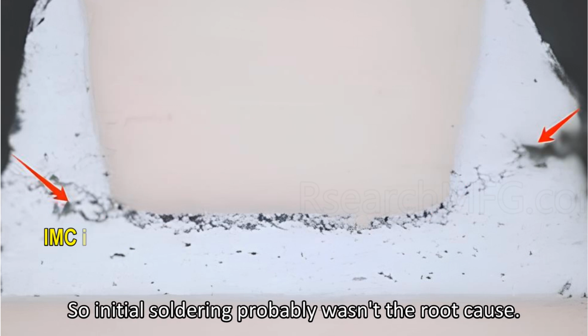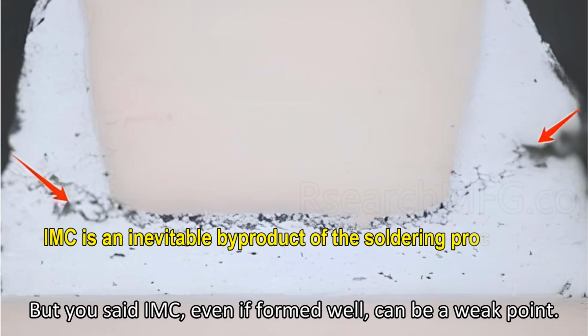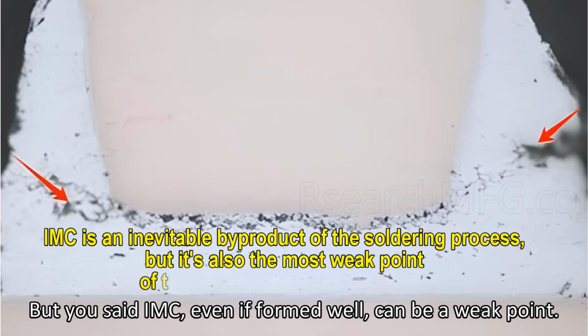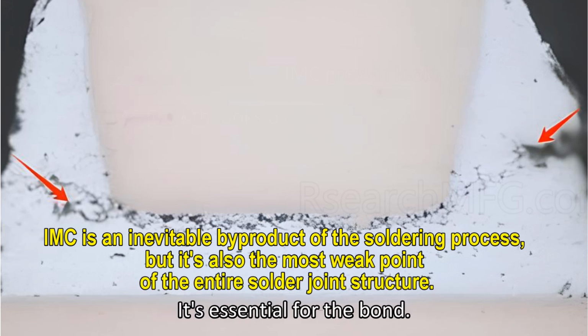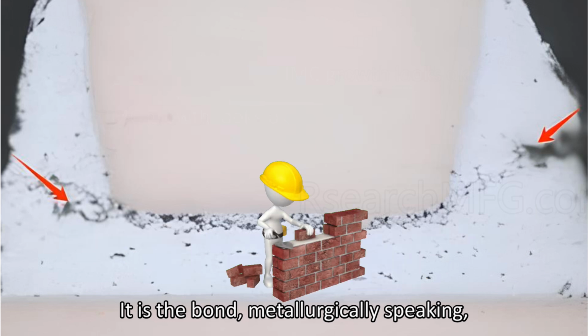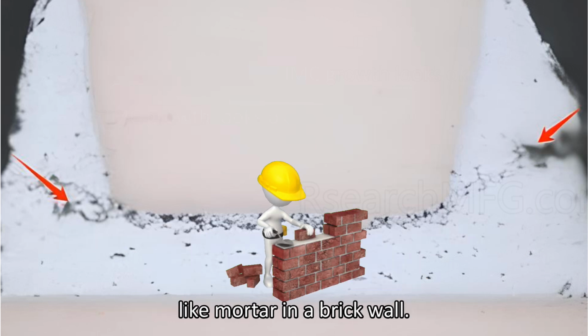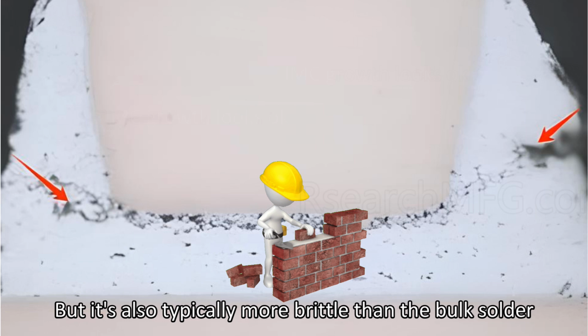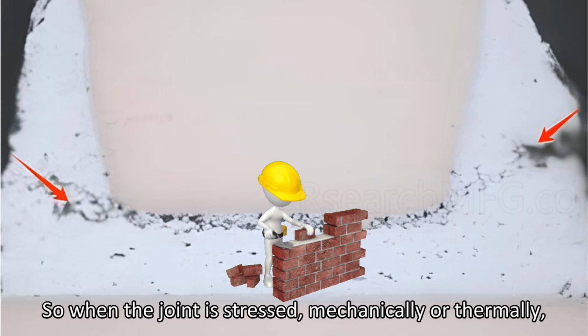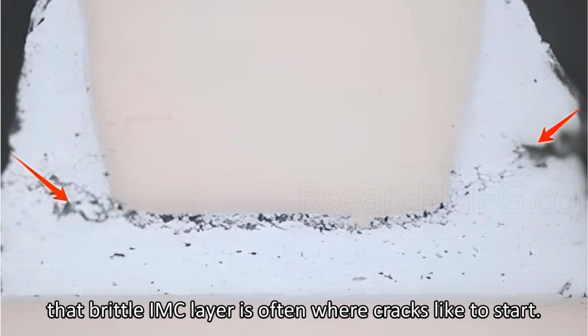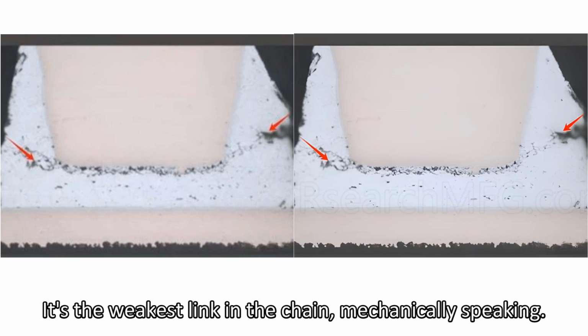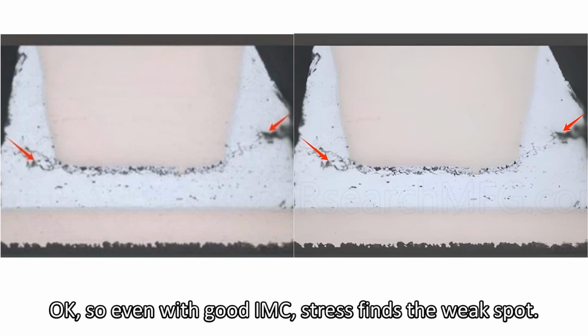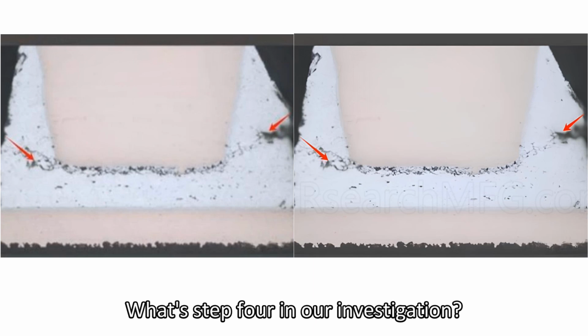Suggests it's likely okay there too initially. So initial soldering probably wasn't the root cause, but you said IMC, even if formed well, can be a weak point. Yes, absolutely. It's essential for the bond. It is the bond, metallurgically speaking, like mortar in a brick wall. But it's also typically more brittle than the bulk solder alloy itself. So when the joint is stressed, mechanically or thermally, that brittle IMC layer is often where cracks like to start. It's the weakest link in the chain, mechanically speaking. Gotcha. Okay, so even with good IMC, stress finds the weak spot. What's step 4 in our investigation?